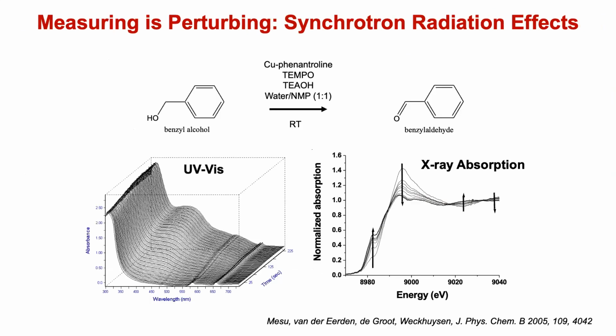I promised you an example: homogeneous catalysis for beam damage. So I showed you temperature effects, and I hope you now understand that it's so important to put in the thermocouple or a second technique to evaluate your system. Here I show you experiments we did because a professor from Delft University approached us; he was active in copper complexes. It's an alcohol oxidation to benzaldehyde, with TEMPO and copper phenanthroline. I'm not a specialist in it. On the left you see the UV-vis. There's a combined setup, UV-vis and X-ray absorption.